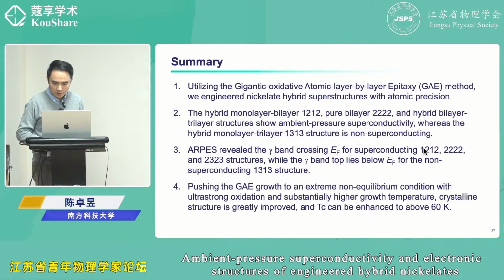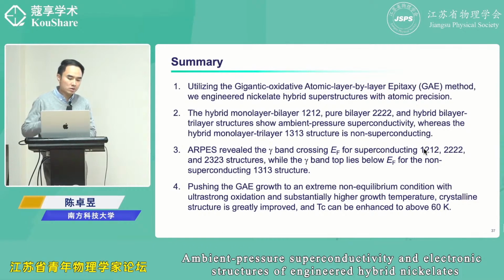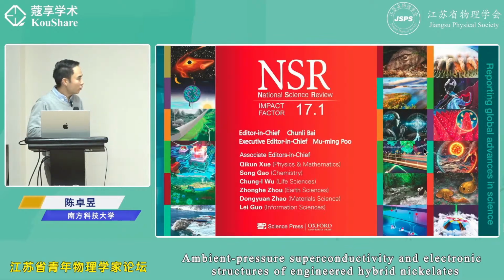Yep, so that's all of my talk today. We use a new method that we call gigantic-oxidative atomic layer by layer, and we engineered these nickelate hybrid superstructures. Some are superconducting, some are not, and we also measured the ARPES of all these structural variants. Then using this growth method, we also pushed to an extreme non-equilibrium condition, and got a TC enhancement to above 60.